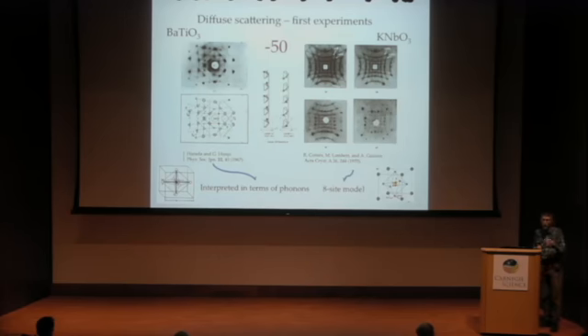So this piece of evidence seems to give a very intuitive and simple understanding of the phase diagram, the temperature phase diagram. Why we, in terms of configuration and entropy, it's very easy to understand that if we occupy 1 of the 8 sites, there is no more diffuse scattering, no more disorder.